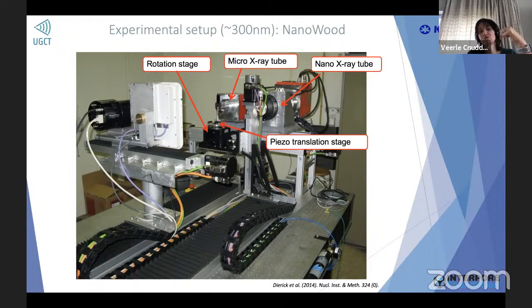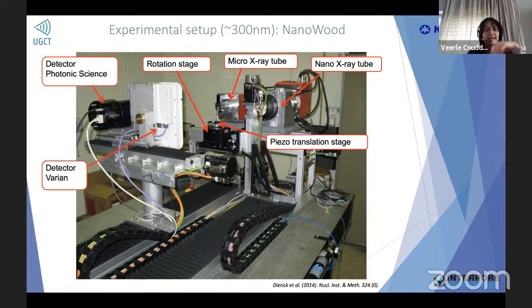And then we have a rotation stage in order to have your sample rotating very smoothly. It's air bearing, so that during rotation there is no shift or movement of the sample. We also have a piezo translation stage in order to position our sample ideally in the center of rotation of the object. And then here we have two detectors in this case also.